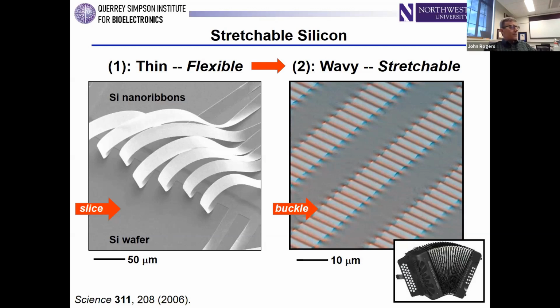And so a silicon wafer is rigid and brittle, partly because the silicon has those kinds of characteristics, but also because the wafer is fairly thick, maybe 0.5 millimeter or 1 millimeter in thickness. And for any material, if you make it sufficiently thin, it becomes mechanically flexible just by virtue of the fact that the bending stiffness scales with the cube of the thickness. And so if you create strategies that allow for nano ribbons or nano membranes to be shaved off of the near surface region of a silicon wafer, you can create a form of silicon that's very flexible.